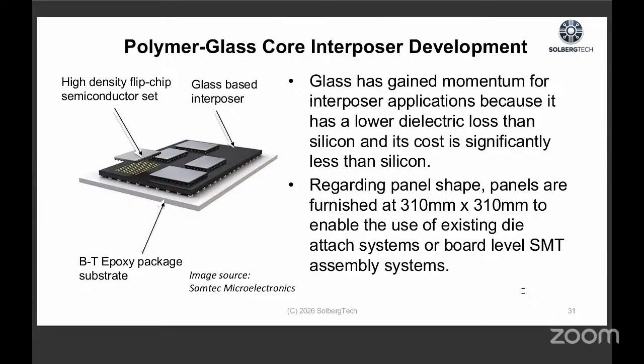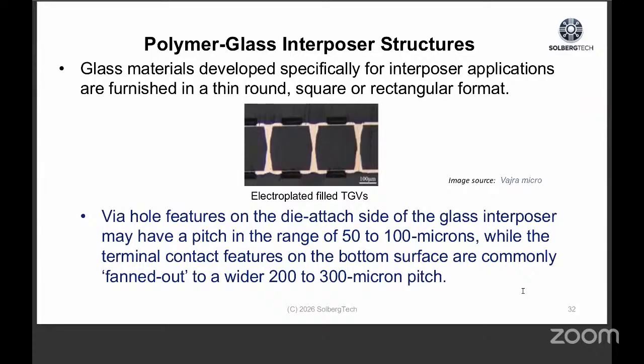It's very tough glass. It's not nearly as delicate as something you'd have over your windows. Okay. So regarding panel shape, the finished size that they're going to be supplying to the user is just slightly over 300 millimeters. And in this way, they can use the existing systems. Next slide. So polymer glass is a unique structure. To drill the holes in this material, it's a series of processes. And the hole features on the die-attached side of a glass interposer have to have a pitch in the range of 50 to 100 microns, while the terminal contact features on the bottom surface are commonly spanned out so that they would adapt to the next level of package substrate. That'd be 200 to 300 micron pitch.